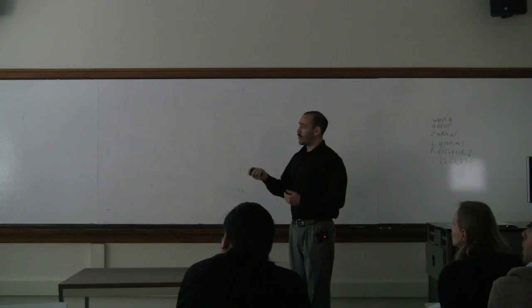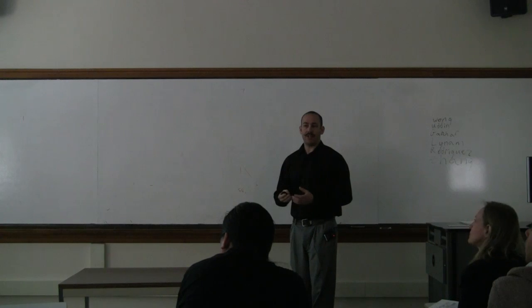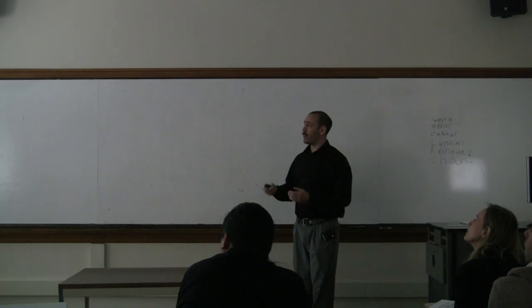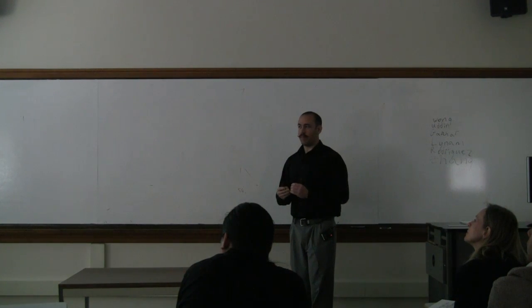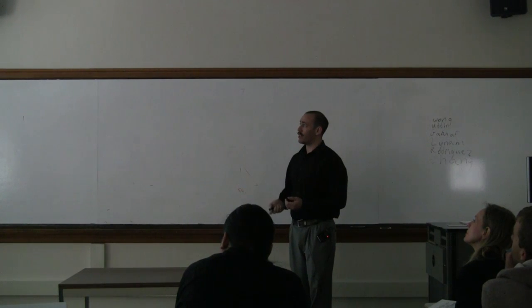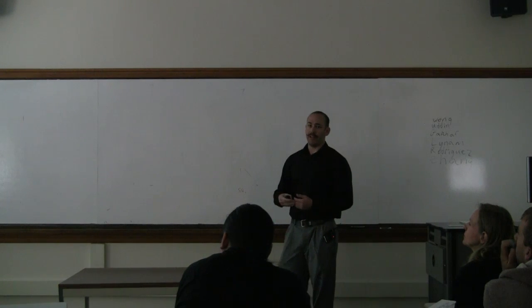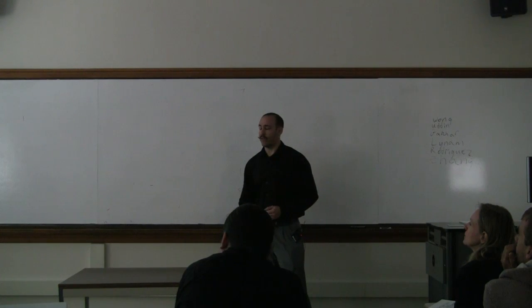Now you have the corrosive solution coming in, and you have aluminum hydroxide forming, and this causes the chromium-6, which is more wanting of electrons, to migrate across this scratch and fill this in, and this reforms the barrier layer of the chromium-3 on the scratch surface of the aluminum alloy.